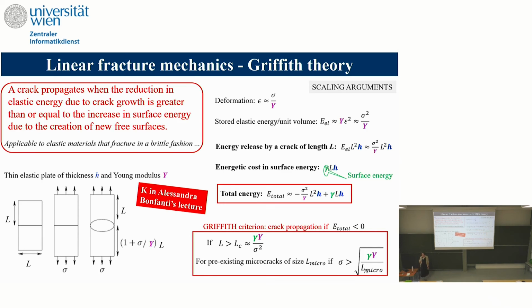And the energetic cost that I have to pay is the cost to create two interfaces, an interface between air and my sample. So it's a surface energy times the surface of my crack, which is L times H. If I make the balance, the total energy is the released elastic energy and the surface energy that I have to create. And what Griffith said is that the crack will propagate if this term is negative.